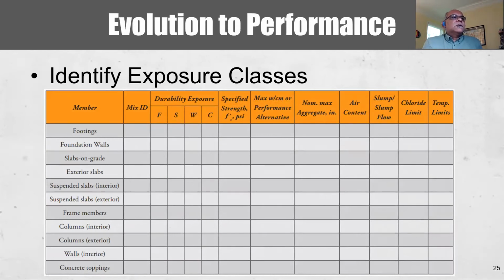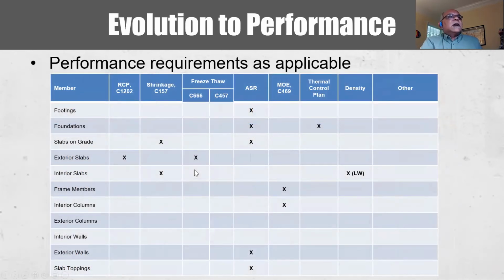These are basic code requirements. Based on the durability, exposure, and the load, you establish the specified strength. If applicable, you specify a maximum water cement ratio consistent with the code. These other details are related to constructability and code requirements. If you need to go further, you can establish types of performance requirements, such as permeability in the first column, shrinkage limits, evaluation of freeze thaw, and alkali silica reaction. And as you can see in this table, these requirements may not be necessary for all the concrete mixtures that would be necessary on a project. So selectively use or establish criteria for the different concrete classes.